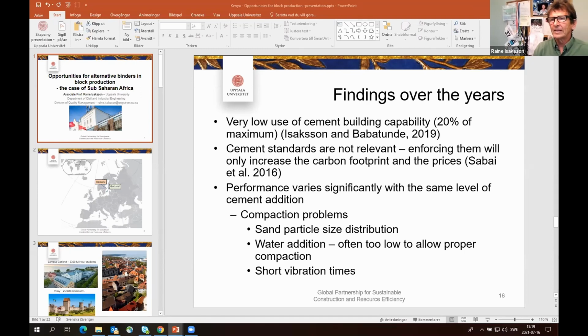And performance varies significantly with the same level of cement addition, but this is often not perceived. A few of the issues that have surfaced in all my studies, of course, is the sand used, but quite often customers cannot choose. They get the sand that they get. Where they could do something is the water addition. Normally too little water is added. If you think of it, if you have 5% of cement and 95% of sand, you need to put quite a lot of water to get that compaction. Otherwise there are big voids and the strength will be very low.